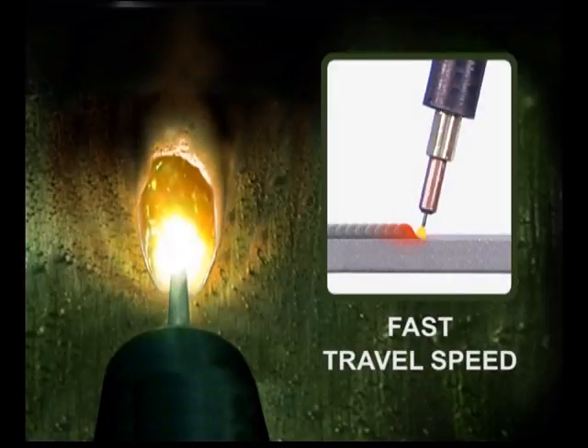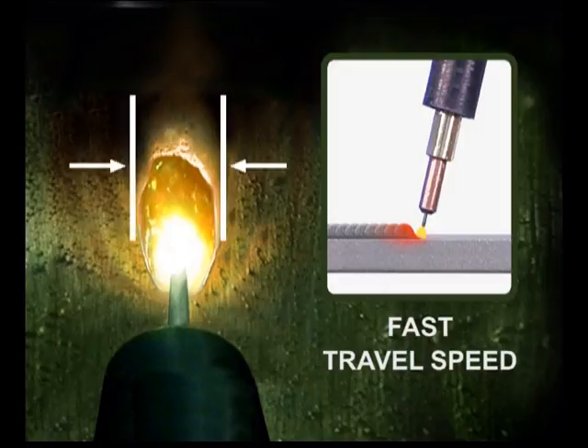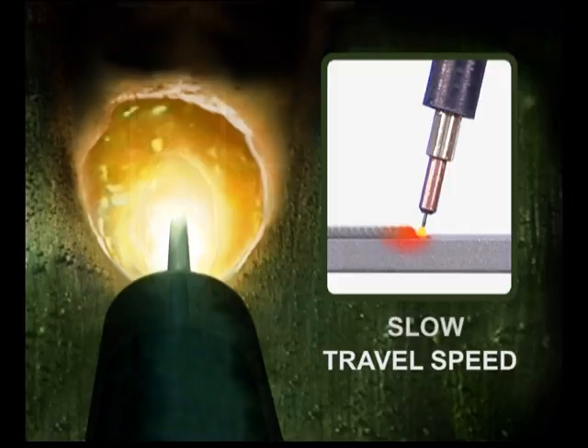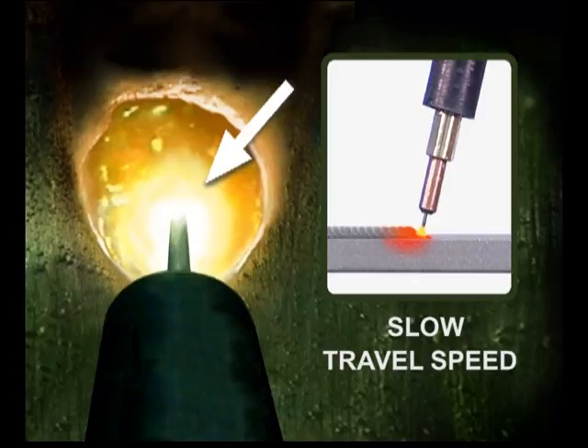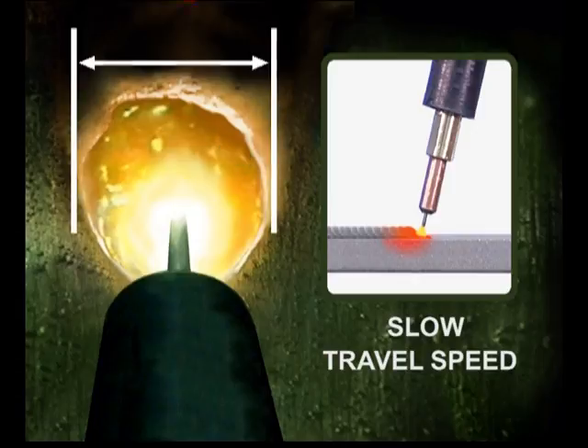If the travel speed is too fast, the metal doesn't have time to heat up. The weld bead will stack up on top with limited penetration and weld fusion. Traveling too slow will generally put the wire and the arc on the weld buildup, causing excessive filler metal deposit and making the puddle difficult to control. Watch the puddle. You need to travel slow enough to allow the molten pool to spread, and at the same time, fast enough to keep the filler metal from becoming excessive and overheating. Then maintain a travel speed that keeps the molten puddle the same size.